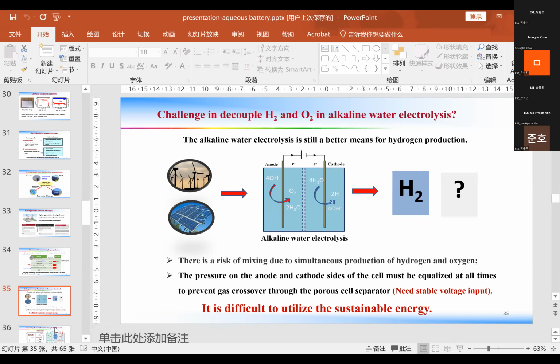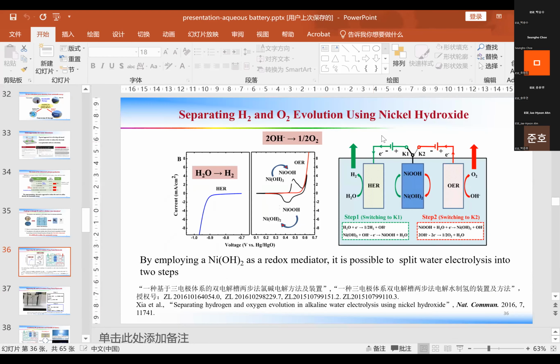Then we use nickel hydroxide, with intercalation for the nickel hydroxide, so we separate the hydrogen and oxygen evolution. The nickel oxidation potential is between the hydrogen and oxygen evolutions. This reaction's potential is higher than hydrogen evolution but lower than oxygen evolution. So we can separate this water electrolysis into two steps.